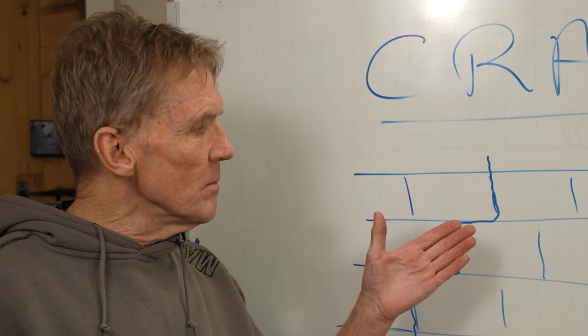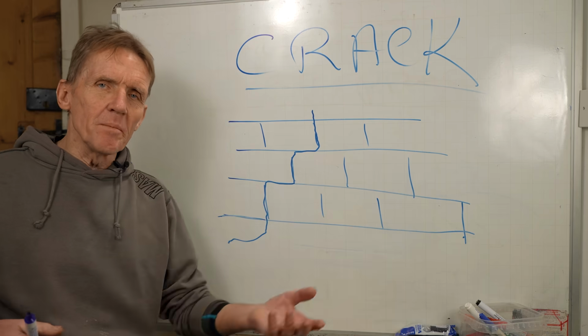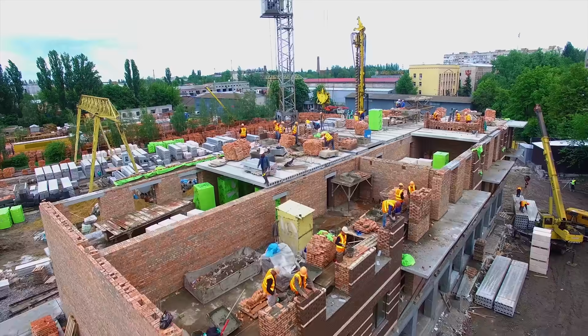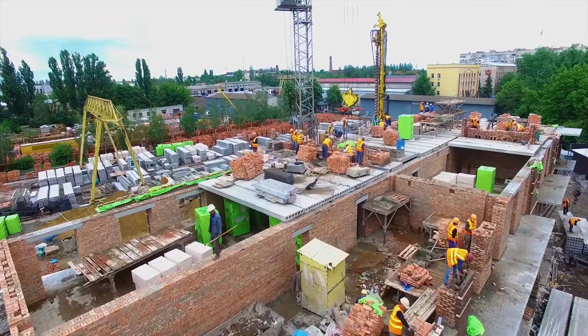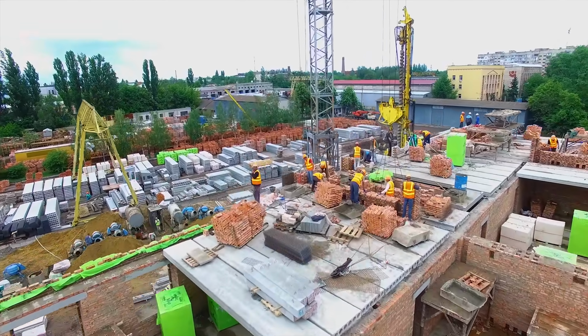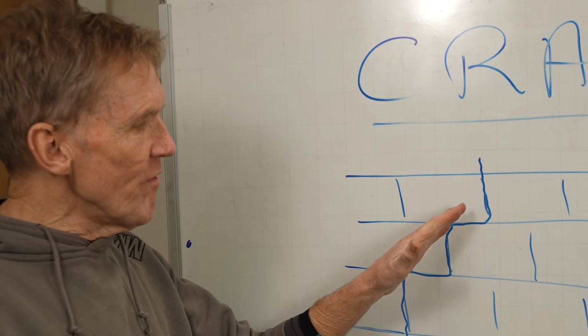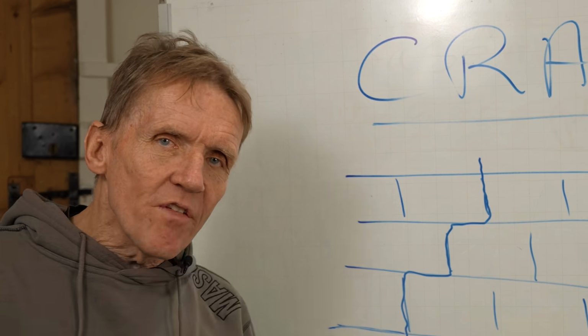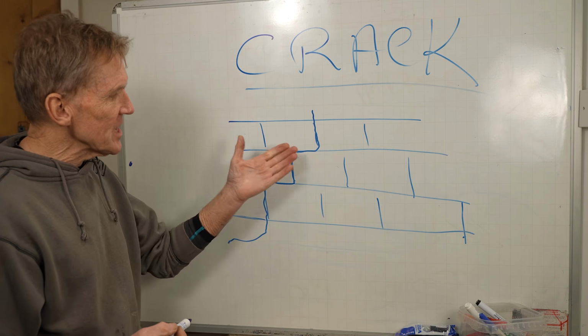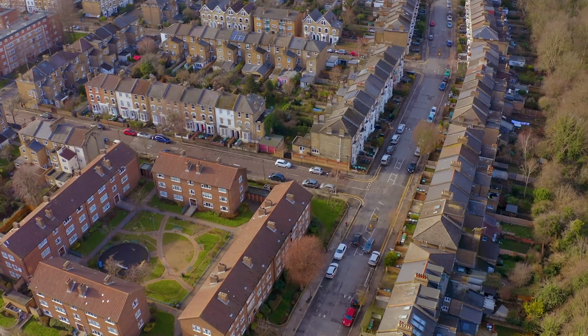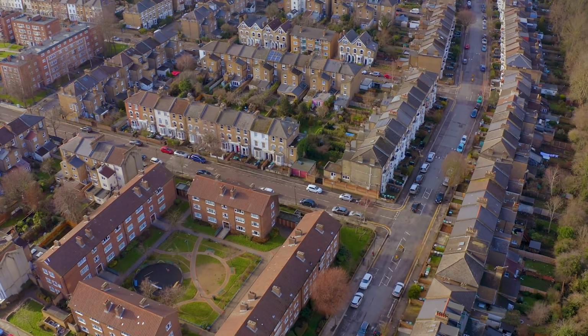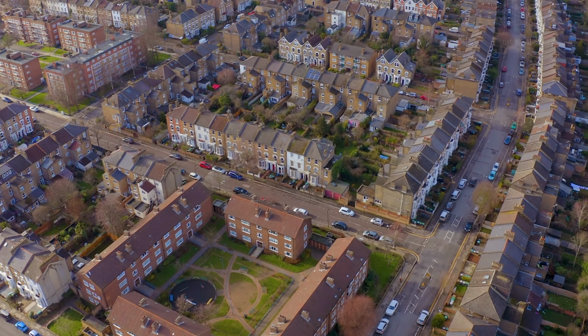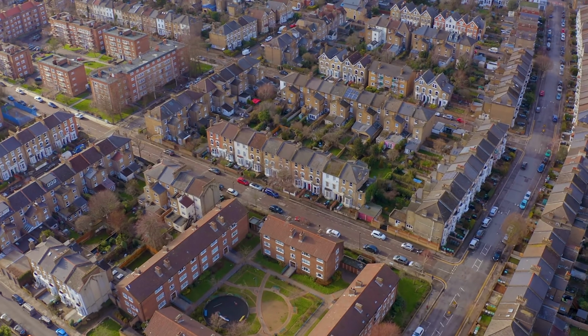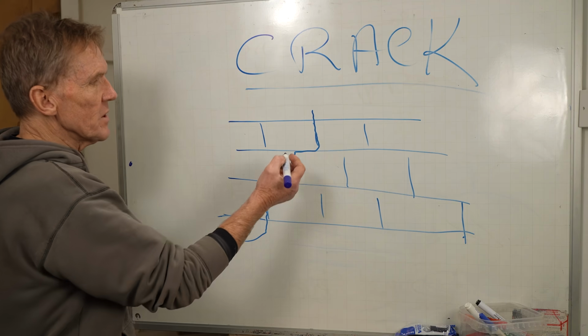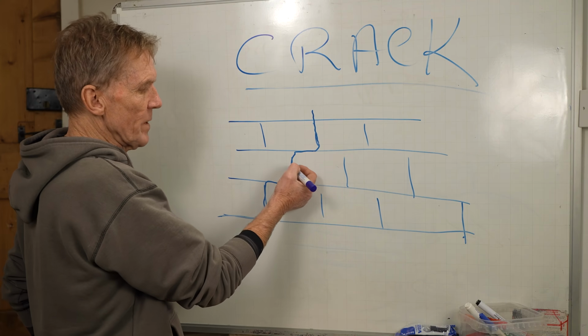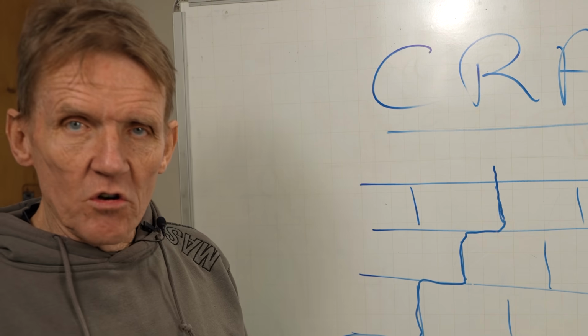That's one of the beauties of brickwork, it is kind of accommodating. And if you don't make the mortar too strong, put a bit of lime in it, 5 sand, 1 cement, then if there is any movement in a building, and let's face it, all buildings move at some time, it's taken care of by this natural give in the brickwork structure, which is a fantastic thing. If you've got an old building, built 100 years ago, as much of the London property was, it's got sand and lime mortar, the worst thing you can do is go poking a nice strong mix of sand and cement in there, thinking that you're going to be sealing that crack up.